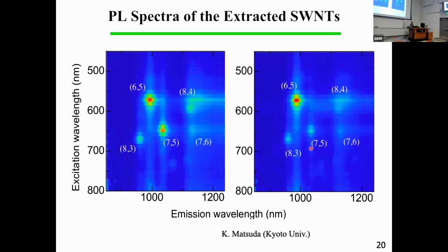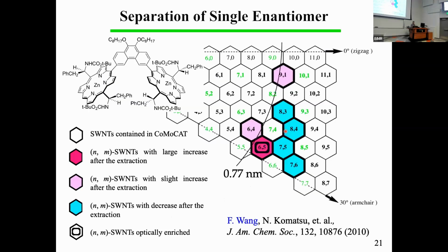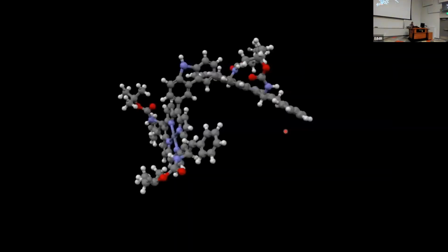And this is the photoluminescence spectroscopy. Unfortunately, the metallic tubes cannot be seen, but anyway, among the semiconducting carbon nanotubes, (6,5) was clearly enriched. Okay, so this is a summary of this part. Our designed nanotweezers can discriminate only one specific (n,m) structure with either left-handed or right-handed structure. So this is a movie showing what is going on in the recognition of the carbon nanotube.